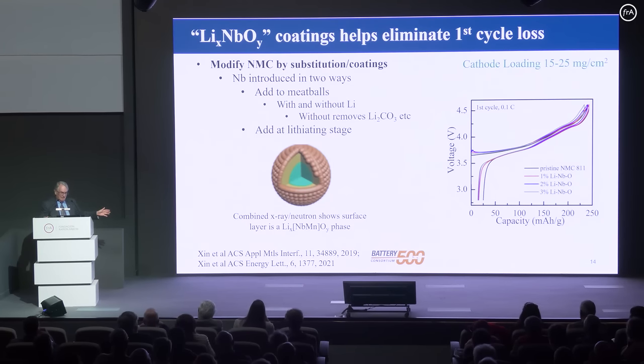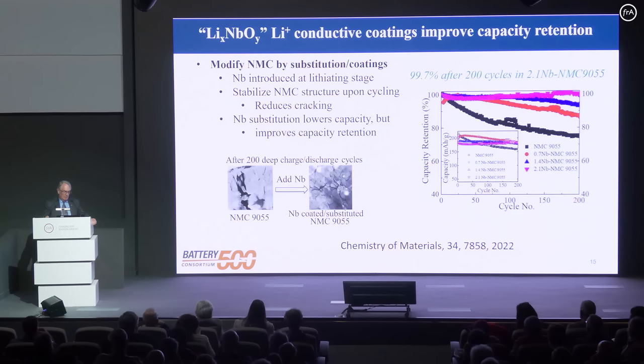If we increase the temperature from room temperature to, say, 35 degrees centigrade, a warm day in Madrid in the summer, we don't have this first cycle loss at all. It all goes away with a slight increase in temperature. But what we've also found using this niobium is we don't lose any capacity on cycling it. So we can charge and recharge these materials hundreds of times, and I'll show you an example here. We've done it 200 times, and this is with 2% niobium in the lattice. You can see there's absolutely no loss in capacity at all. We have a lower initial capacity, which we have to solve, but we found that if we substitute these lattices, we can make them extremely stable.